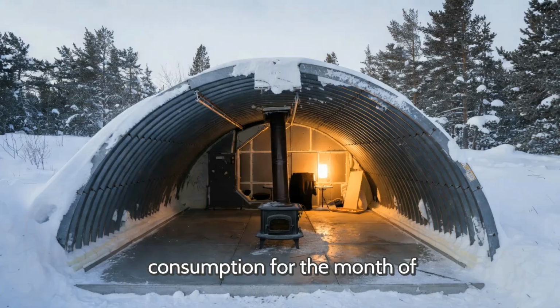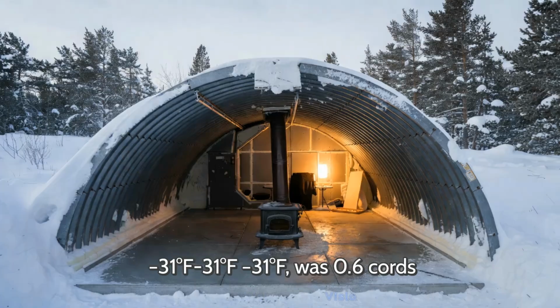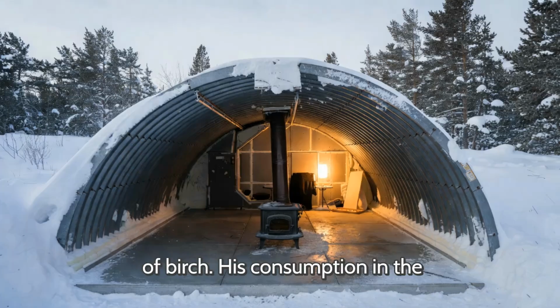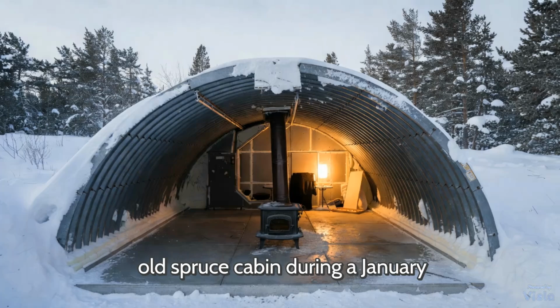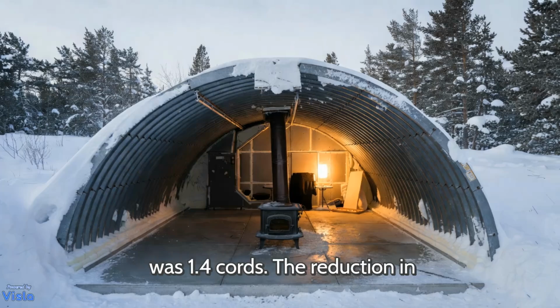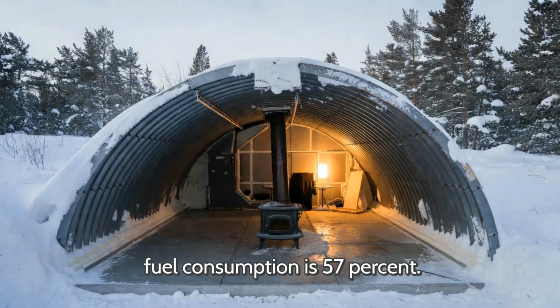Harold's wood consumption for the month of January, during which the mean exterior temperature was minus 31 degrees Fahrenheit, was 0.6 cords of birch. His consumption in the old spruce cabin during a comparable January mean temperature was 1.4 cords. The reduction in fuel consumption is 57%.